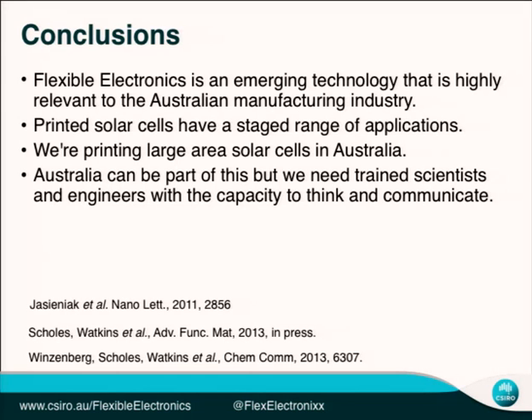Third row. Yeah. Which one's winning the race at the moment, these or the nanoparticles? The nanoparticles have got higher efficiencies, but we've printed the organics on large area. The nanoparticle stuff began later and has accelerated really quickly, and we're talking with different people about that. There's existing manufacturers of CdTe cells that we're talking with that might be interested in adopting that. So it's not a competition between these two things, or with silicon.